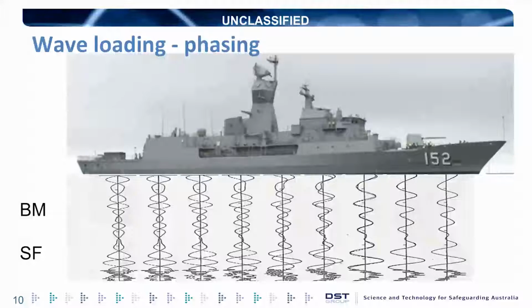These plots are the shear force and bending moments at each section along the ship's hull, and you notice towards the bow the scales are different so that they align on top of each other. You see the shear force and bending moment diagrams are actually in phase with each other, whereas towards the aft of the ship, the phase of the shear force and bending moment diagrams are separate. What that really means is towards the bow of the ship, I'm getting principal stresses that are alternating in one direction. So if I've got a weld that's perpendicular to that, is that more damaging than a weld that's parallel to that? And this is an issue that I don't believe has been resolved today.